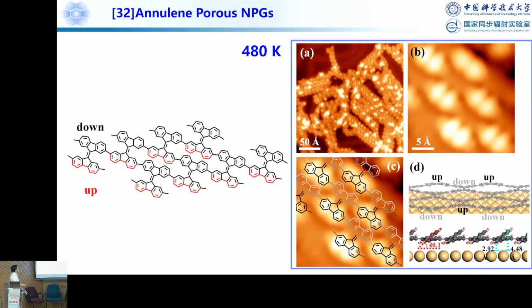Now if you increase the temperature, you can see we form this structure on the surface. Some are bright because you form this tilt up and this tilt down, like proposed here. Because the gap in between is really narrow, you can see this tilt up. The DFT calculated result finds that the lowest part to the surface is 2.9 angstrom, which is even shorter than normal graphene ribbons on surfaces. That means there is a strong interaction with the substrate.